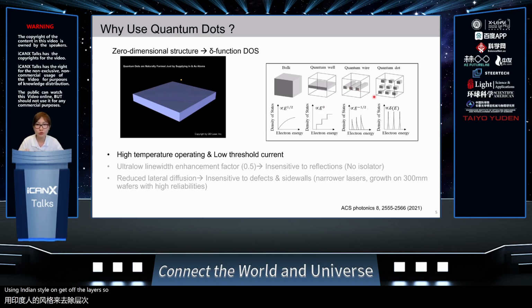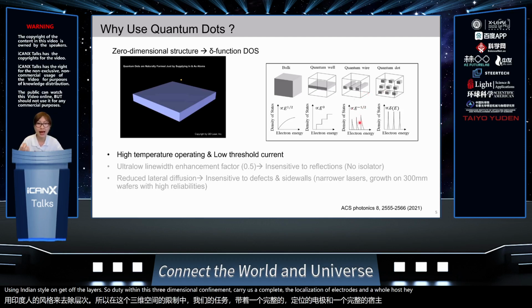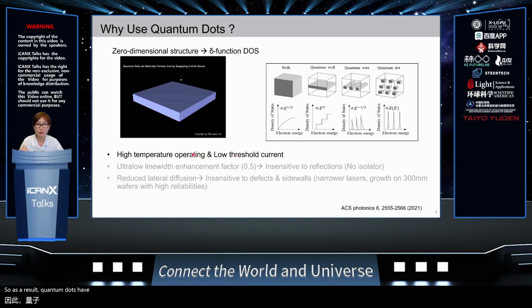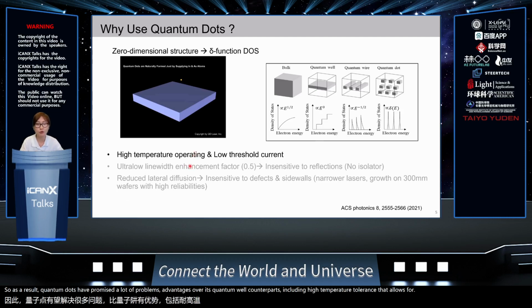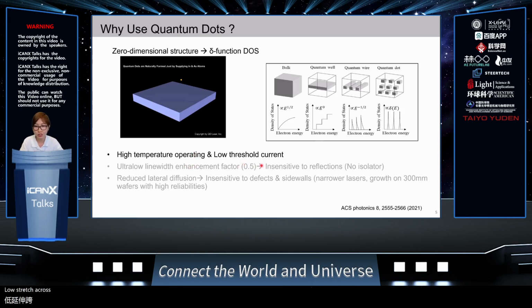Due to this three-dimensional confinement of carriers, a complete localization of electrons and holes can ideally give rise to a sequence of delta function-like density of states possessing atomic-like degeneracy. As a result, quantum dots promise a lot of performance advantages over their quantum well counterparts, including high temperature tolerance that allows for robust CW operation up to 220 degrees C, and low threshold current that is capable of supporting low energy consumption.